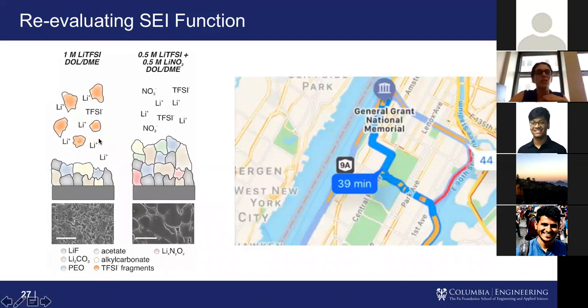So we can tell ourselves, if we use this TFSI electrolyte here, we're going to be taking this route where there are some roadblocks, and we know exactly where they are. We know the molecular structures that are causing them. If we use this electrolyte that combines TFSI and lithium nitrate, we're going to take this other route where it's much smoother. We're going to get there more quickly because we have better conduction through this SEI layer.